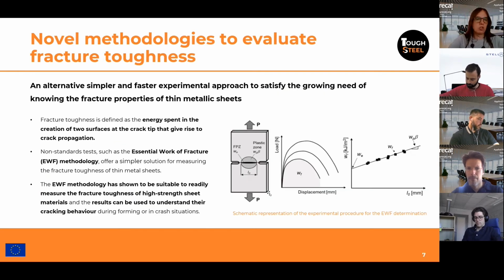In fracture mechanics, the fracture toughness is defined as the energy spent in the creation of two surfaces at the crack tip that give rise to crack propagation. The standard methods or tests to measure this fracture toughness are complex and also involve exhaustive specimen preparation, and their application in thin sheets is often difficult. As a consequence, the fracture toughness of advanced high-strength steels is not applied by the different steel makers, part makers, or the OEMs in the design of structural and safety-related components in automotive. Thus,